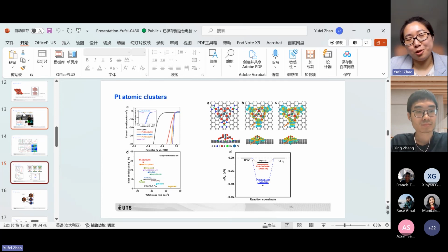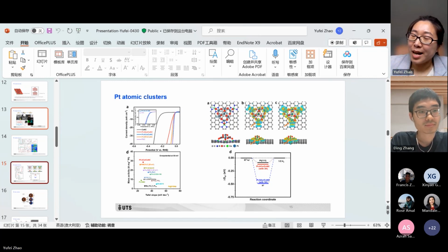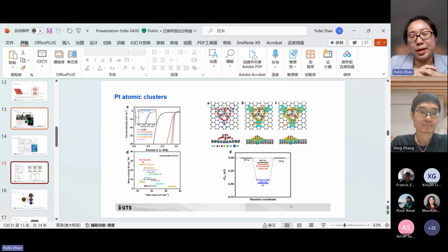But for the precious metals, it's also a little bit different. If we want to work in acidic conditions, normally for the HER side we would like to use platinum. If we want to work in alkaline conditions, maybe ruthenium is a better choice. But for OER, currently we don't want to use iridium because it's too expensive, so we use ruthenium as an alternative. For alkaline conditions, I think ruthenium can work for both HER and OER. But for acidic conditions, we can combine platinum with ruthenium. If we only use platinum or only ruthenium, maybe it's not that good.